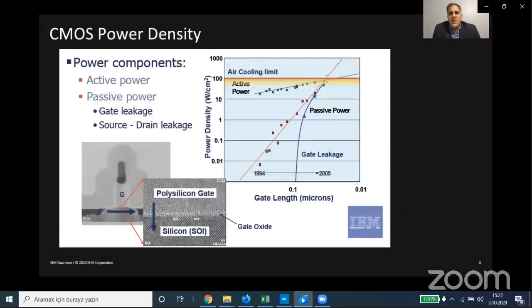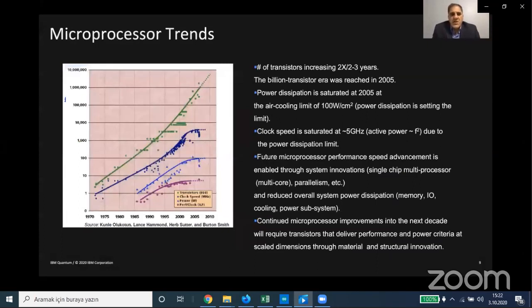In fact, when we go below 100 nanometer node, the power density, which is the passive power plus active power, is approaching the air cooling limit of 100 watts per square centimeter. This high power, which is near the air cooling limit, is limiting the clock speed to be saturated at around 5 gigahertz for microprocessors. Microprocessor active power goes as frequency squared, and that limits it to around 5 gigahertz. So future microprocessor performance advancement, in addition to boosting transistor performance, requires system innovations, and that involves single chip multiprocessor, multi-cores, parallelism, and so on.